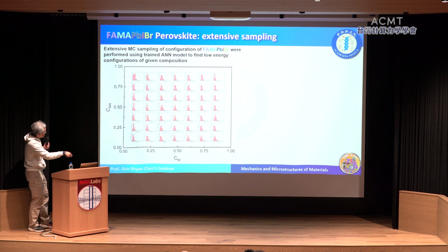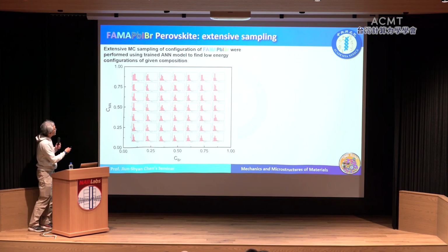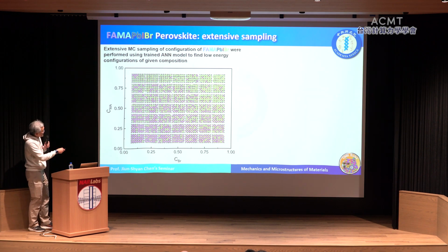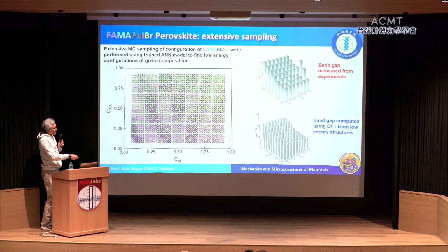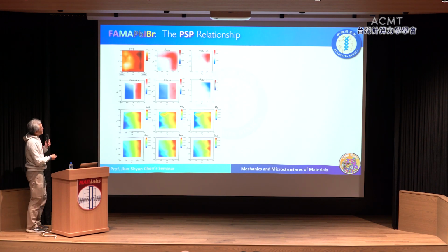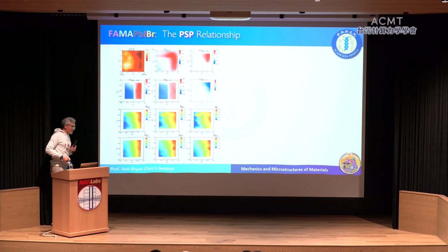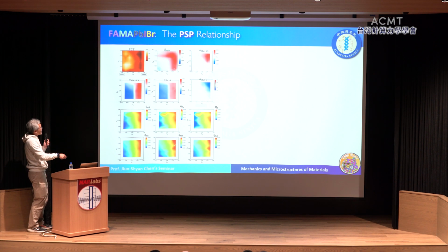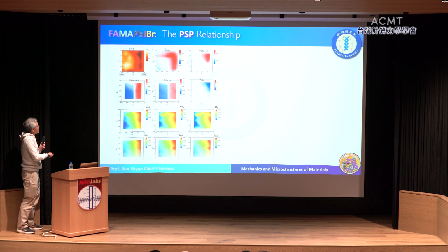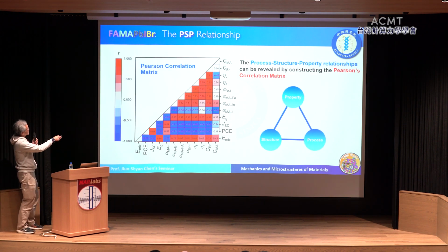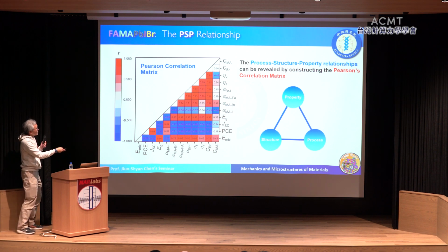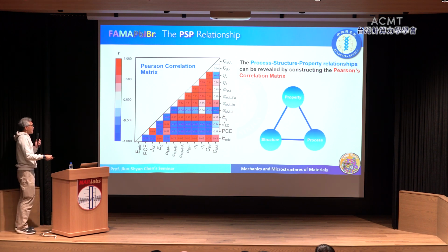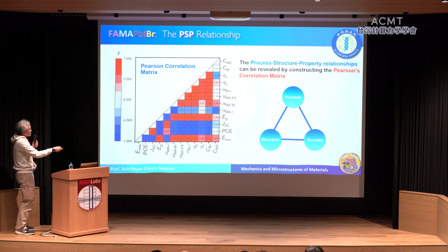So this is the concentration of bromine, and this is the concentration of methylammonium. Then we can isolate all the low energy structures and use them to compute the band gap and compare with the experiments. Furthermore, because the neural network model is very efficient and fast, it allows us to map a lot of physical and mechanical properties of this complex perovskite, and then we can use that to build a Pearson correlation matrix, which allows us to reveal the process-structure-property relationship of this complex perovskite material.